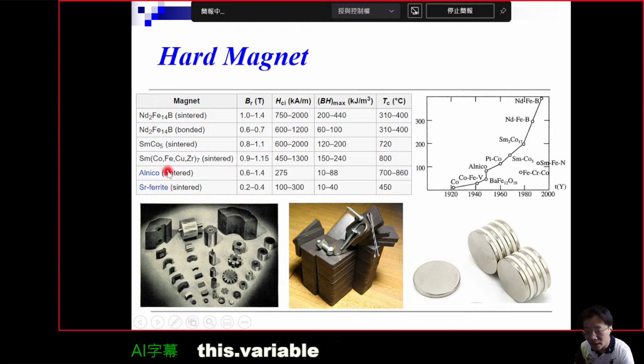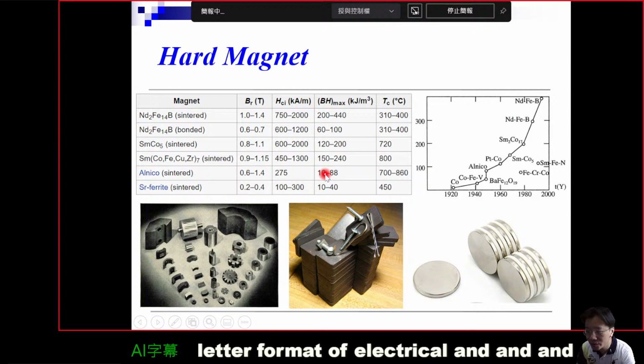There's another type of hard magnet, Alnico. You can divide this word into three elements: Alnico means aluminum, nickel, and cobalt, so Al, Ni, and Co. It is an alloy with also very good remanence, a little bit less than the neodymium magnet, and a little less coercivity than neodymium iron boron. Actually, its magnetic energy product is not so good, only 10 to 88 compared to the neodymium iron boron magnet, but its working temperature is high, reaching 700 to 860 degrees Celsius. So that is also good.